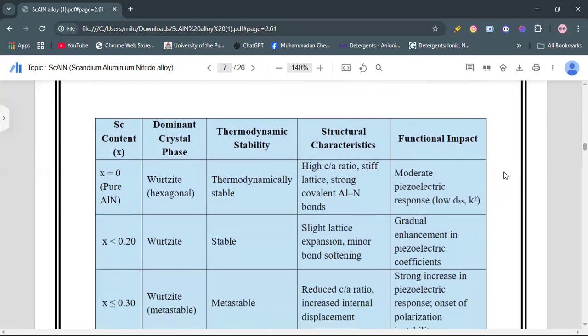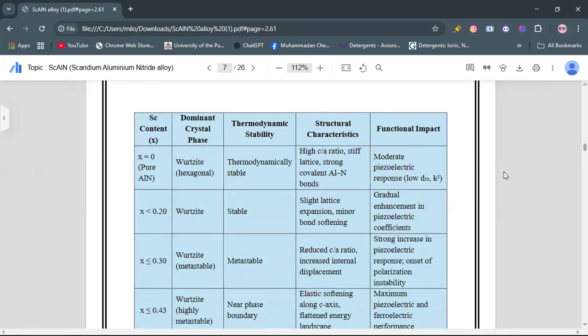Here is a table which shows different scandium concentrations and their different functional effects. For example, if we have scandium concentration 0, x equals 0, then the dominant crystal phase is wurtzite hexagonal. This is thermodynamically stable, with a high c/a lattice parameter ratio, a stiff lattice, and strong covalent aluminum-nitrogen bonds, and